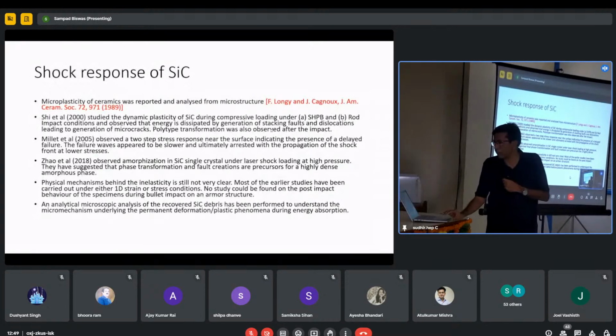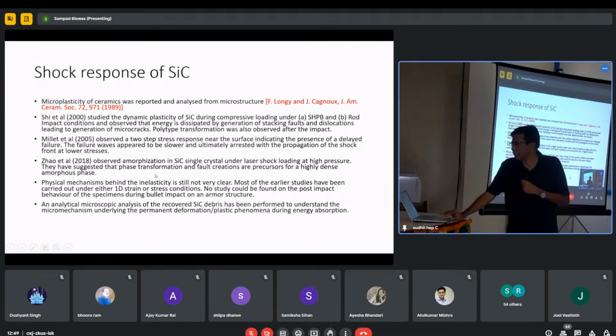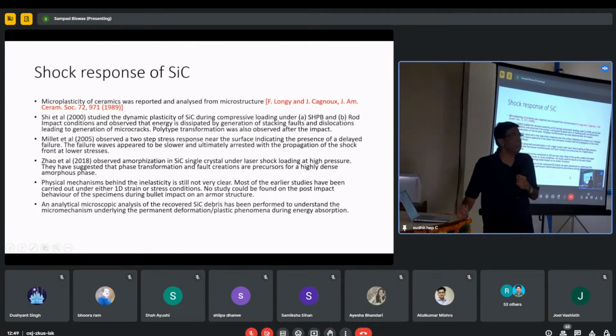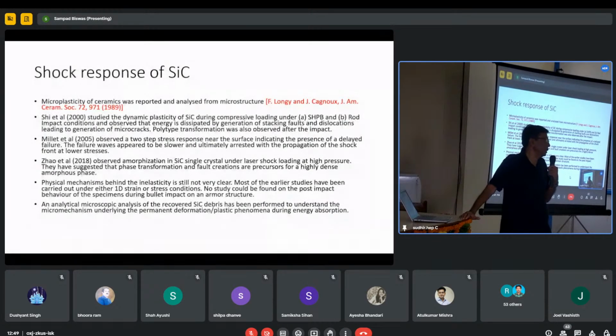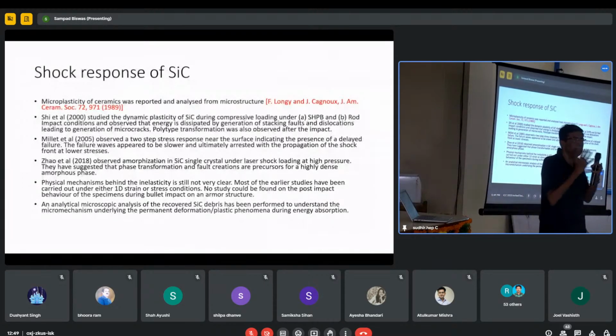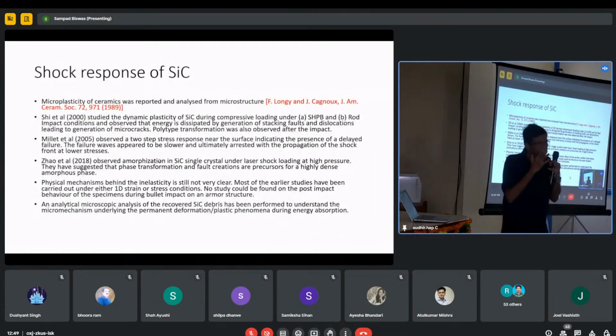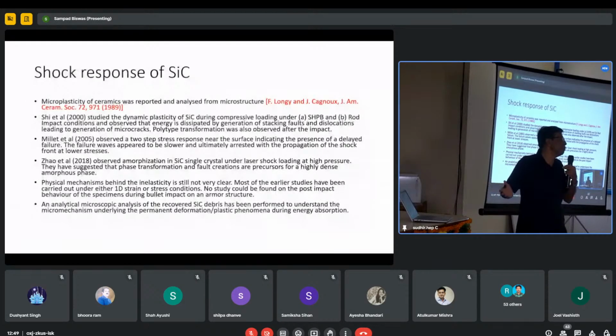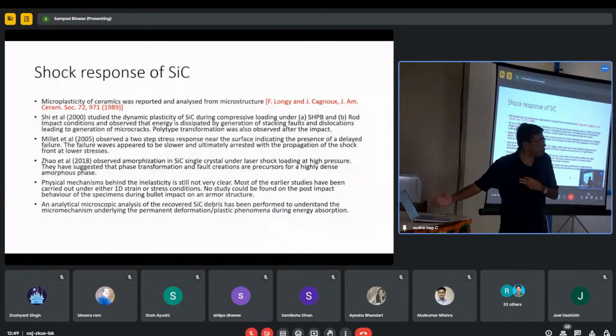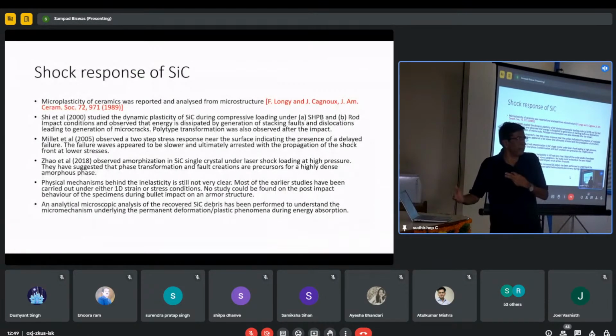So lastly, some people have found that amorphization takes place. That means when you are hitting it with a bullet, when you are giving it extra shock pressure, crystalline to amorphous phase formation occurs, and from there recrystallization also takes place. These were the mechanisms, and some people have observed it. We will also show you how it happened in our case.